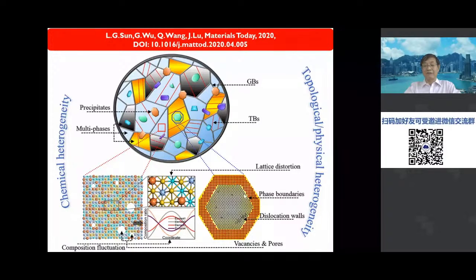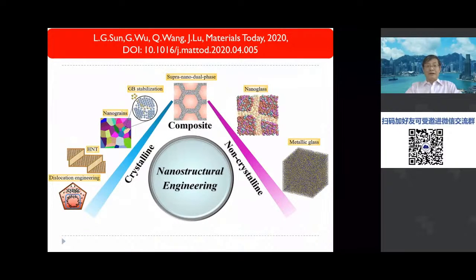So in this case, we generate different phase boundary and dislocation wall. And for the composition fluctuation, we can generate a lattice distortion. So all this heterogeneity, if we manage it with intelligence, then that can help to generate a dual property for us. To narrow down the different research that we develop, we start from metallic glass, then we can work on nano glass, so the range is around 100 nanometer. And today I want to introduce you a so-called super nano dual phase material.